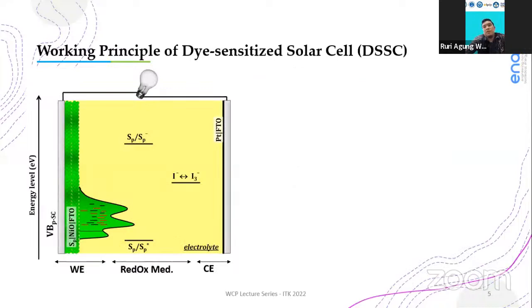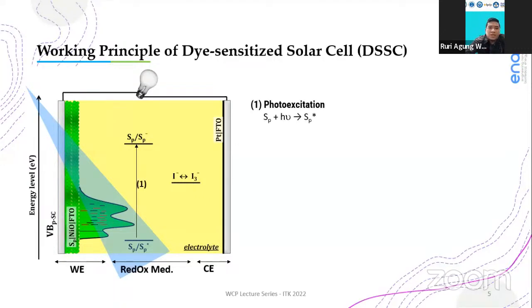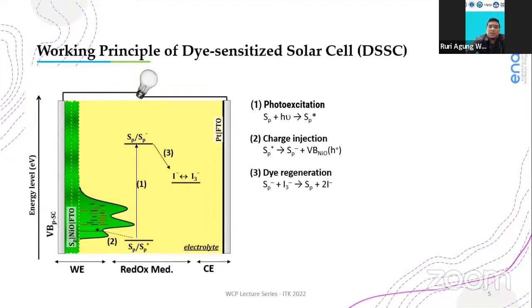The working principle of the P-type dye-sensitized solar cell is illustrated in this animation. The solar cell consists of dye-sensitized nickel oxide as the working electrode, an iodine-based electrolyte as redox mediator, and platinum-coated conductive glass as the counter electrode. Upon irradiation, the dye is excited, followed by hole injection from the excited dye to the valence band of the nickel oxide. Subsequently, the reduced dye is regenerated by triiodide and redox mediator regeneration occurs, yielding an external current flow.